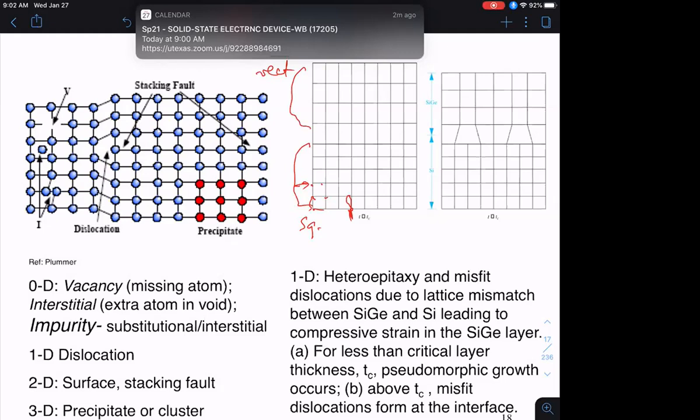Now, then at these lattice points, you have to put in a physical entity, which is called a basis, and that's shown on the left-hand side, where the basis happens to be, say, a single atom, these blue atoms. But in general, the basis could be more complex. Okay, so it could be a group of atoms that have to be put at every single lattice point in the same orientation. Otherwise, those correspond to defects.